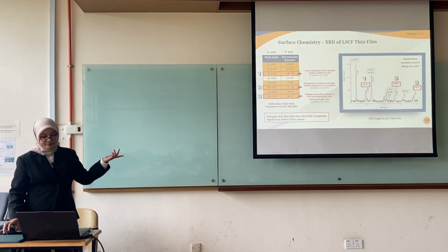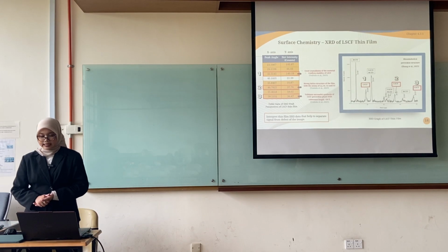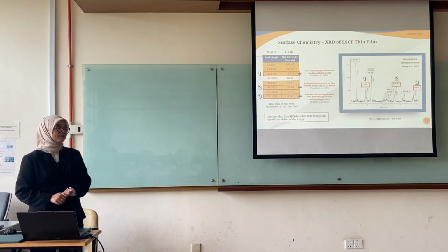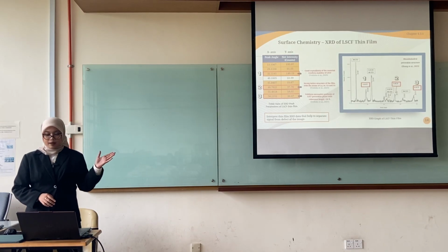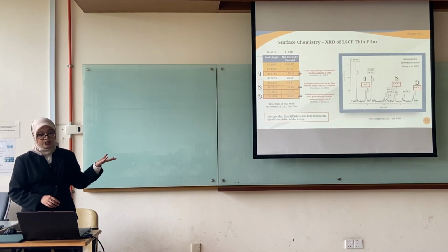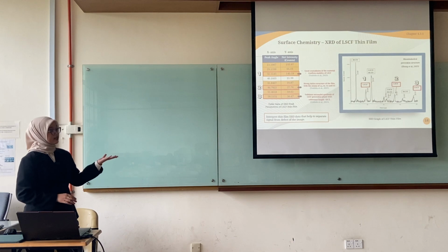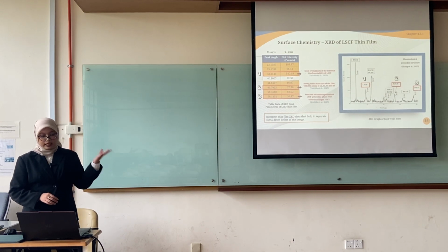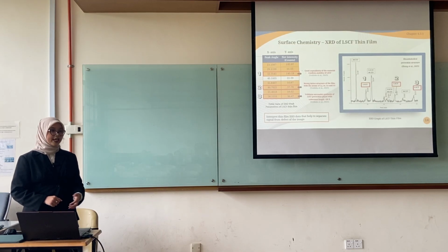In addition, the peak highlighted in the white box is considered a defect signal because it doesn't correspond to the main perovskite structure, but instead arises from secondary phases within the thin film. So in conclusion, this study ensured that the analysis focused only on the stable perovskite structure of LSCF.